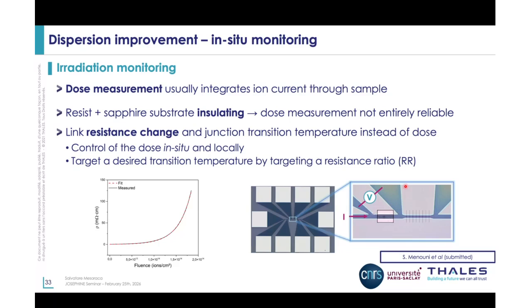And for example, regarding the irradiation, an important measurement of it is the dose applied to each sample. Since our samples are made by YBCO deposited on top of an insulating substrate, plus they have a resist on top to protect the sample from being irradiated entirely and not only in the junctions area, it's very insulating. And the way we measure nowadays the dose is actually by integrating the current flow into the sample. So that creates a not entirely reliable way of measuring the dose, especially between runs, especially between different samples.